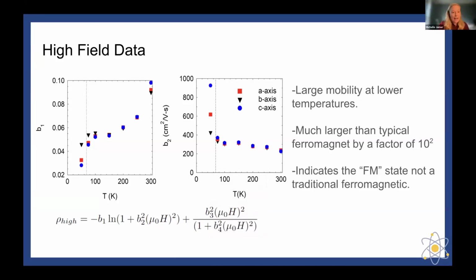Yeah, so in our most recent study that was published, I believe Joe Prestigiacomo was the lead author on this, and I think Steve Bennett was the last author. I'm the second author on it. The films were grown on STO, so strontium titanate. I think that was seen to be the best substrate, but the great news about this material is that it is thermodynamically stable. So you can technically grow it on any substrate, you just might have a secondary phase, unfortunately. So you can still grow it on silicon. In order to get a really nice thin film though, I think STO is needed.